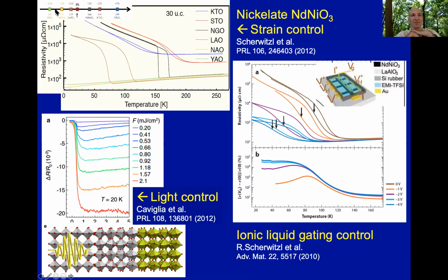Some of these substrates, like this one, correspond to what's called compressive strain, namely a smaller lattice spacing than the bulk lattice spacing. Those correspond to so-called tensile strain, namely elongating the lattice spacing. And you see that for those ones, you can completely suppress the metal insulator transition, while for those ones, you can actually move it around more or less at will. So this is a beautiful example of strain control using the ability to fabricate thin films on controlled substrates.